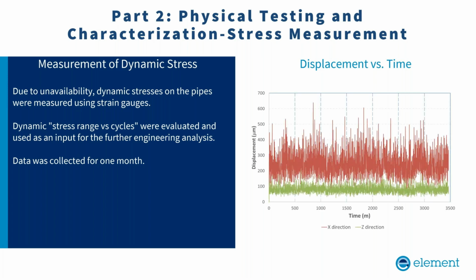After doing this on-site testing, monitoring the health of the material, it was also necessary to understand the forces acting on this asset during operation, because the data was not present with the customer. However, this data was very important for further remnant life assessment. So after doing replica and metallographic work, strain gauges were installed at different critical locations of the component, and strain versus number of cycles was collected over a period of 1 month.